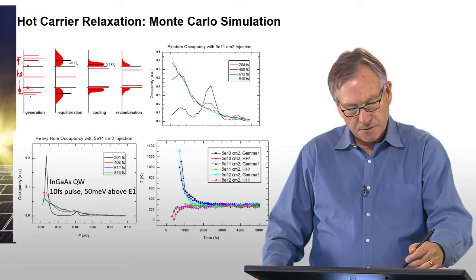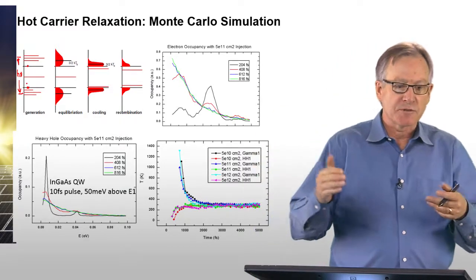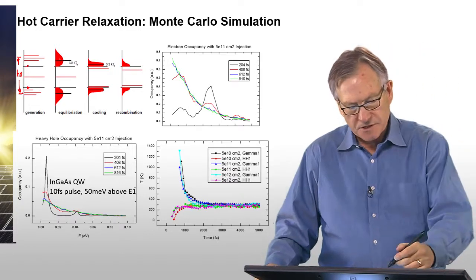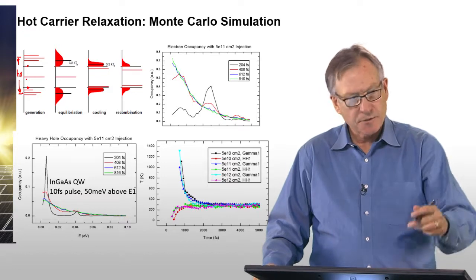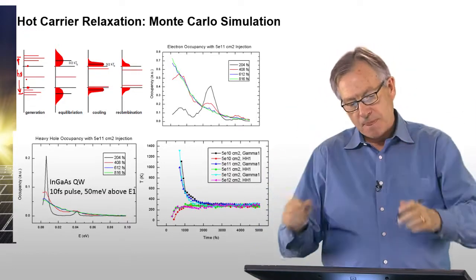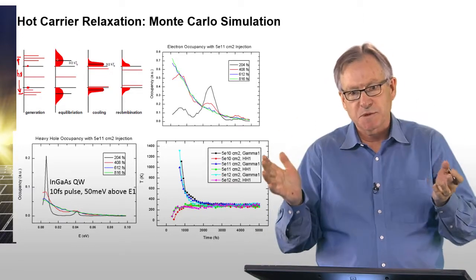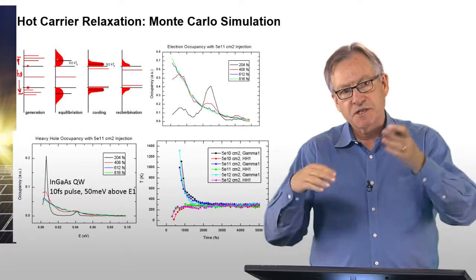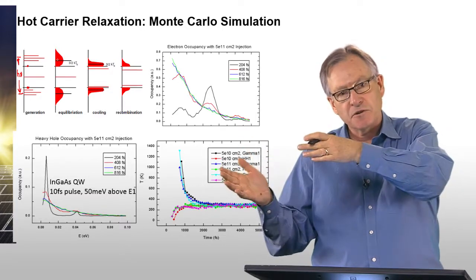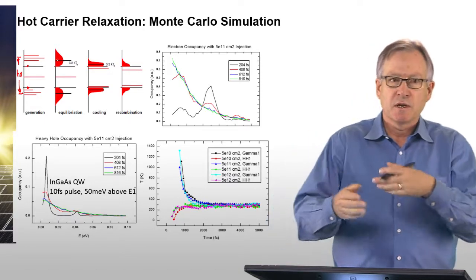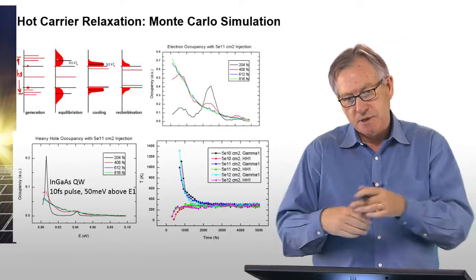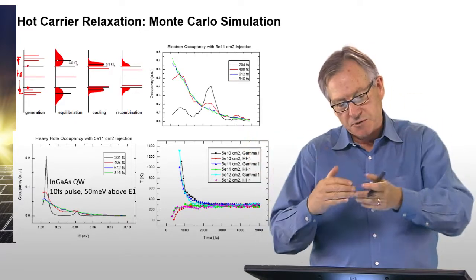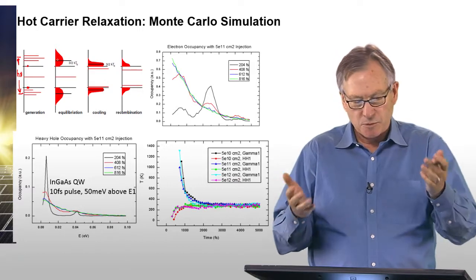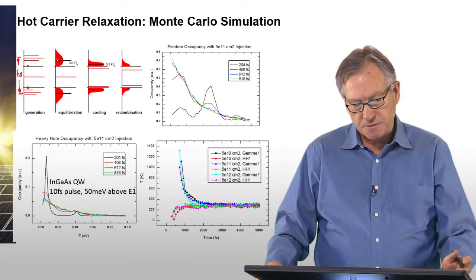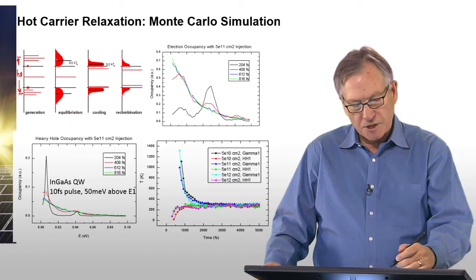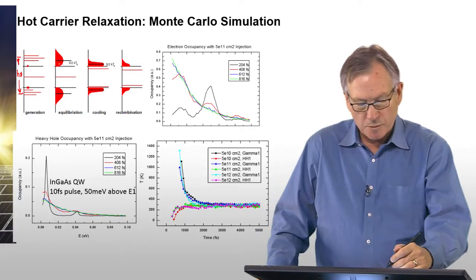The electron energies are up here, the hole energies are down here, and they have nothing to do with the energy of the absorber or the crystal. And then as a function of time, these carriers interact with one another, they exchange energy, they scatter, and basically broaden into a sort of Maxwell-Boltzmann distribution. In fact, this is the process that's involved when a system starts out at non-equilibrium and evolves to equilibrium. It goes through this process of thermalization in which energy is exchanged among the particles, and it goes from a completely non-equilibrium distribution to basically a sort of classical distribution like a Maxwell-Boltzmann, or for electrons it would be the Fermi-Dirac distribution.